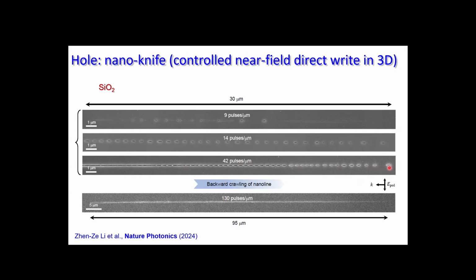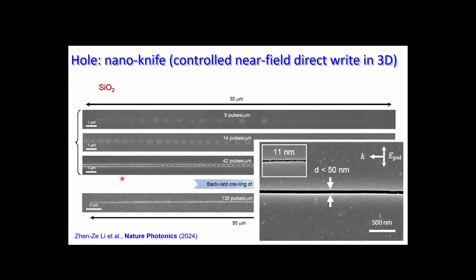And it's also very obvious that they are not getting wider. The width is defined by a natural ability to modify and then to etch out the modified volume. And this is a different scale, so it's all 100 microns length, which is modified into a single channel, which is very narrow. Because HF is etching silica regardless of whether it's modified with laser or not, it's a question of time, how much time you use immersing into etch.